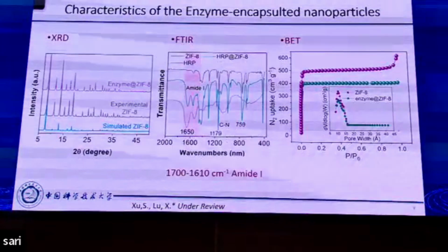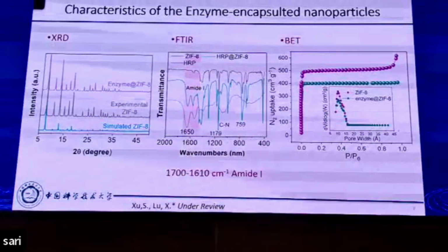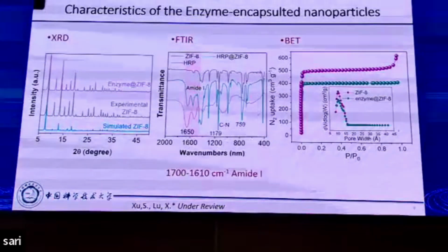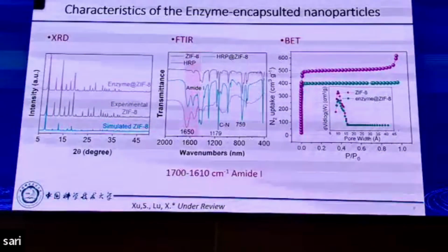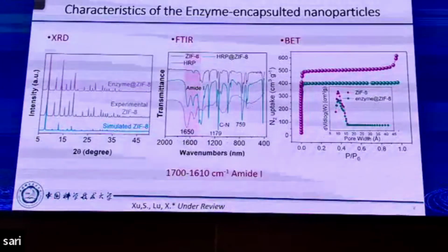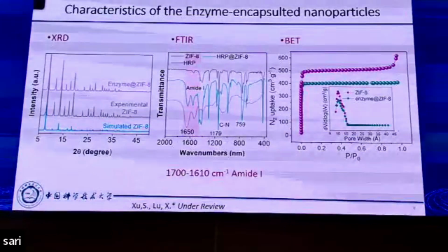So basically, to evaluate how this enzyme will affect the crystalline structure and pore size of these nanoparticles. The good thing is that, regarding the crystalline structure in XRD, the presence of enzyme does not affect the crystalline structure of the ZIF materials.